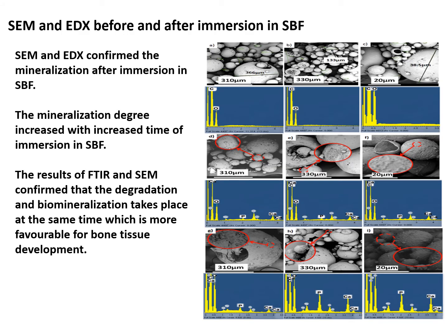This is how we tested the mineralization on the surface of these microspheres, and we can see here before immersion in SBF, and this is after immersion in SBF, and we can see and confirm by the scanning image that there is a precipitation of minerals, calcium phosphate minerals, as confirmed by EDX elemental analysis.